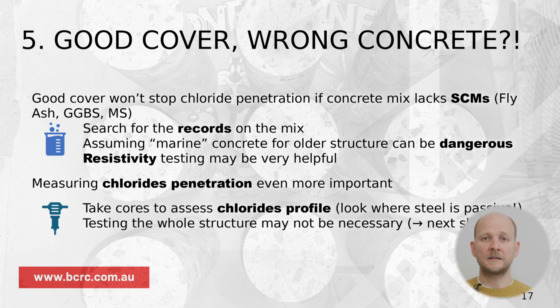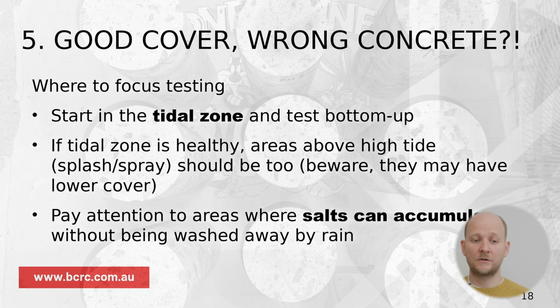It's fairly inexpensive and very helpful test to confirm your assumptions. The next step is understanding how chlorides penetrated, how deep chlorides penetrated into your surface. Yes, it does require taking some cores and a professional subcontractor who understands what they're doing, as well as lab testing, but it provides you essential information about how your structure is behaving, especially if you're looking into a 20, 30, 40 years old structure. It does give you a real understanding about how quickly chlorides are getting in, and it's extremely helpful for residual life assessment.